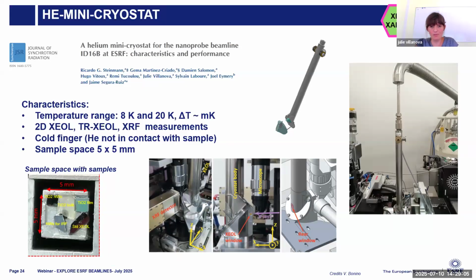And so here you have several pictures of this cryostat that we can mount on the sample stage. And you see here we have the fluorescence detector coming on the side. So the cryostat can be used with the fluorescence, XEOL, and time-resolved XEOL setup. It works between 8 and 20 K. And what is important to know is that the technology that is used is based on the cold finger technology, so it means that there is no contact between the sample and the helium.